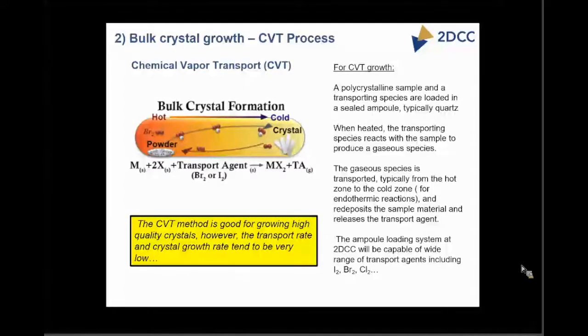The takeaway from this process, it's a very good method for growing high-quality crystals, but it tends to be limited by the transport rate and growth rate. So, for doing research samples, this is a good way to generate material.